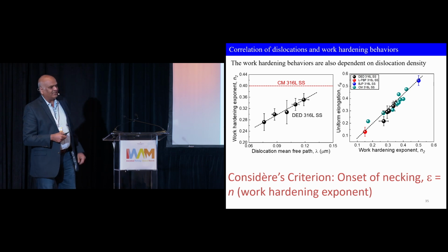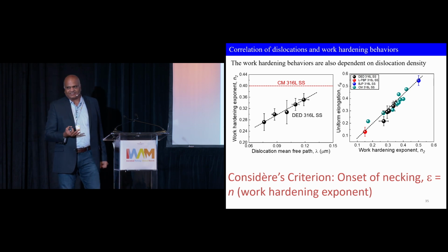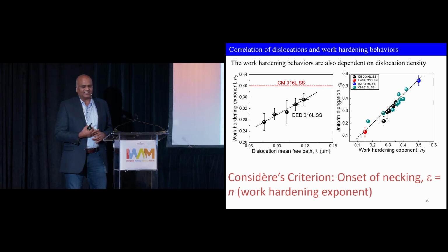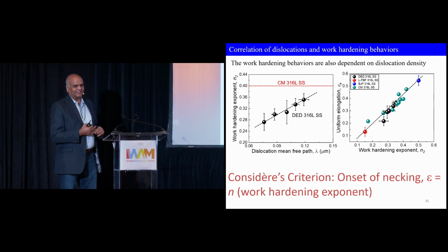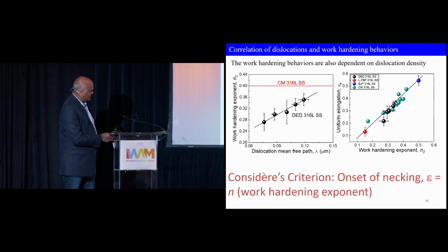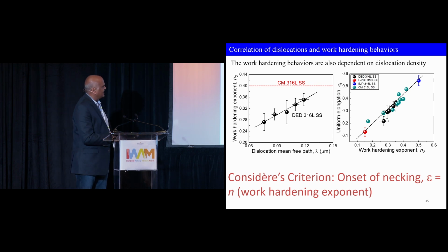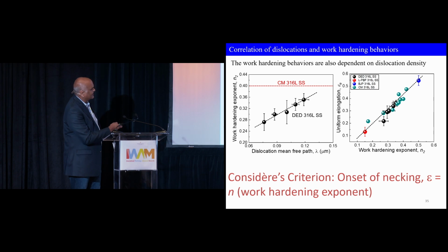And that's why the work hardening ability decreases - it's a little more technical for this audience, but there is a Considère's criterion that we teach. As the work hardening exponent decreases, the uniform elongation, which is the ductility of the material, reduces. So this is what it tells you.